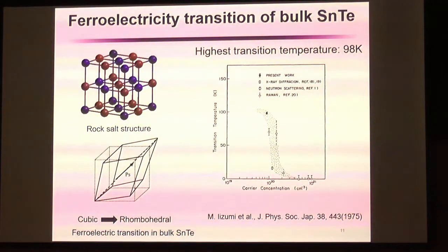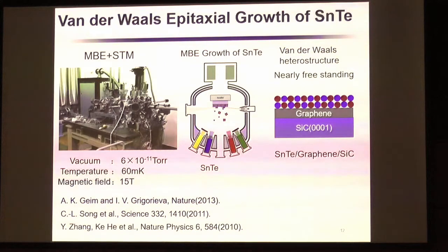It's really a surprise to us. So how did we get very good thin films? Actually, I think substrate choice is very critical. We chose a graphene-terminated silicon carbide substrate. We also tried growing these thin films on the silicon surface, but we found that the interface is hard to control.